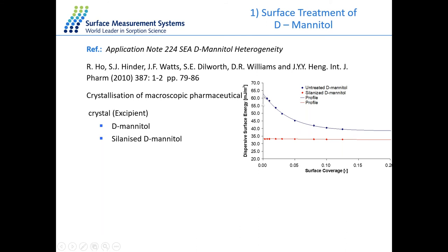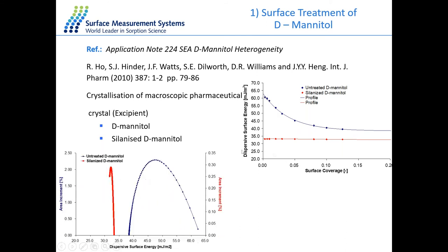And this is the surface energy profile for both of the materials. We can also do the point by point integration of the surface energy profile, and this will give us the distribution profile for the surface energy. The x-axis of the distribution gives the surface energy values, and to interpret the distribution, the wider the gap for the peaks on the x-axis, the more heterogeneous the sample is. In this case, the untreated D-mannitol is much wider compared to the silanized D-mannitol, which is much more uniform, or more homogeneous, compared to the untreated one.